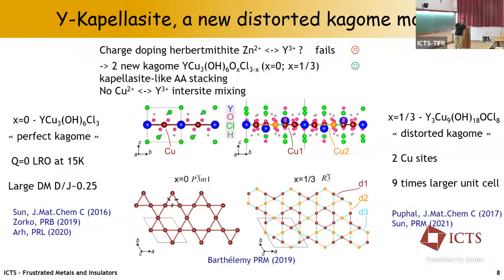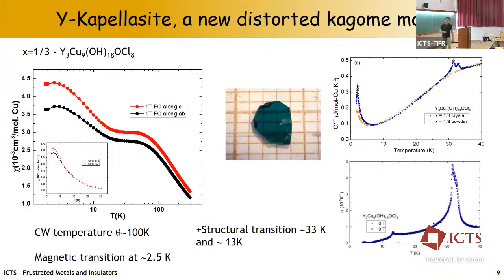I like it quite a lot because if you look at just one layer and one perfect hexagon, you will see that besides the distortion, we still have six-fold symmetry around this hexagon. Namely, these triangles there are connected by a six-fold rotation. So it's a distortion, but it retains some quite high symmetry. I'll tell you a bit more about that later. So let me first show you some initial characterization of the material. I should maybe speed up a bit. This is the susceptibility versus temperature.